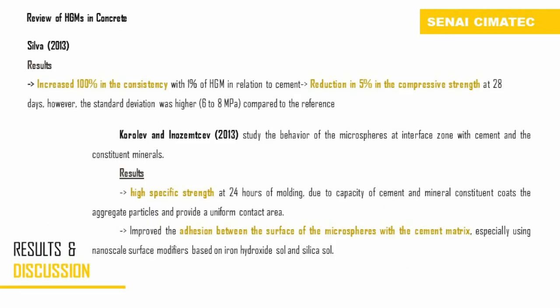In the Silva dissertation, a gain of 100% in consistency was obtained with the addition of 1% HGM. However, the resistance is reduced by 5%. The standard deviation is higher, so the reduction in compressive strength cannot be assumed statistically significant. Another work, conducted by Korolev and Inozemtsev, studied the interface zone between the cement and the constituent minerals. The authors obtained the following results: high specific strength at 24 hours of molding, due to the capacity of the cement and mineral constituents to coat the aggregate particles and provide a uniform contact area, and improved adhesion between the surface of the microsphere and the cement matrix, especially using nanoscale surface modifiers based on iron hydroxide and silica.